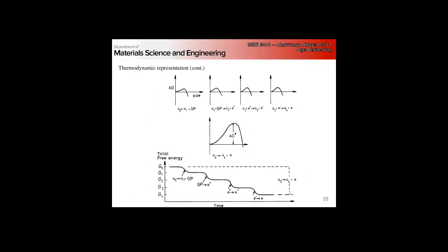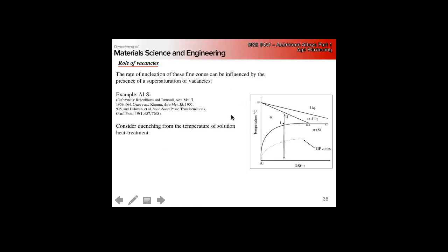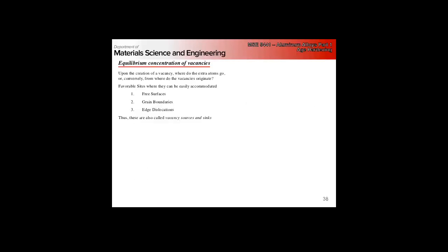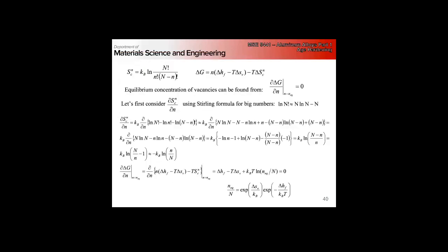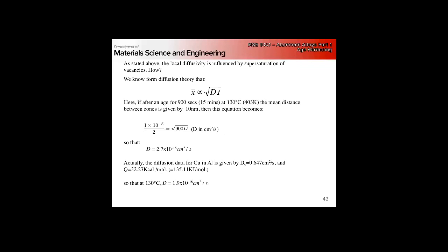And how going in sequence gives us a small nucleation activation energy for each one, compared to a very large activation energy for going right from alpha to the thermodynamic phase. We need vacancies because that gives us enhanced mobility, right?